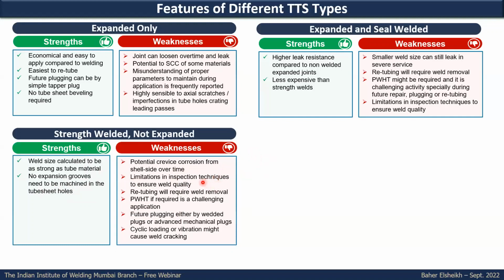And also there is the limitation on the inspection technique, which we said is applicable for all weld joint types. Retubing in the future will be required: removing the weld, conditioning the bevel of the tube sheet again, and re-welding. And if post-weld heat treatment is required, it's also not an easy application, especially during repair or retubing in the future. Future plugging cannot be only taper plug.